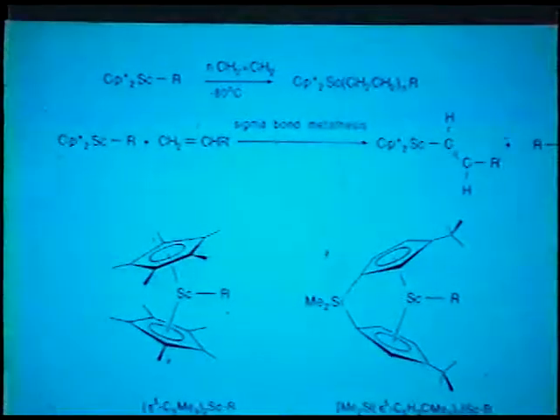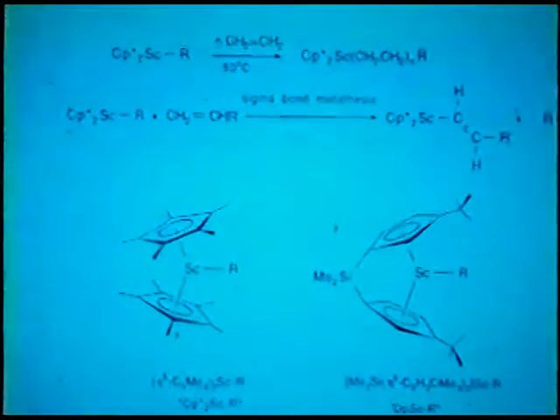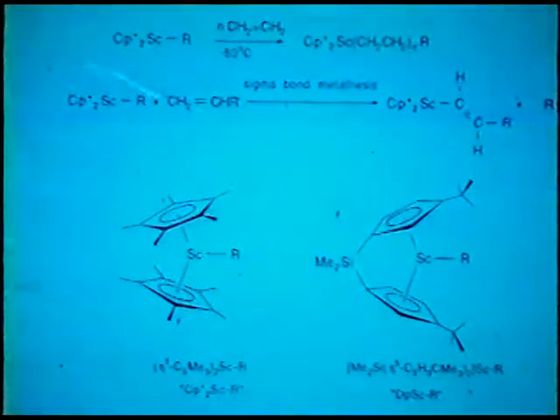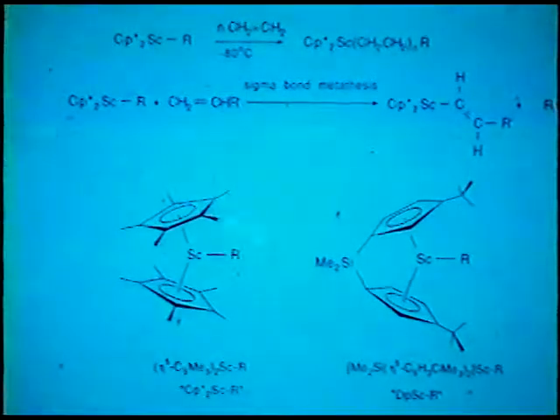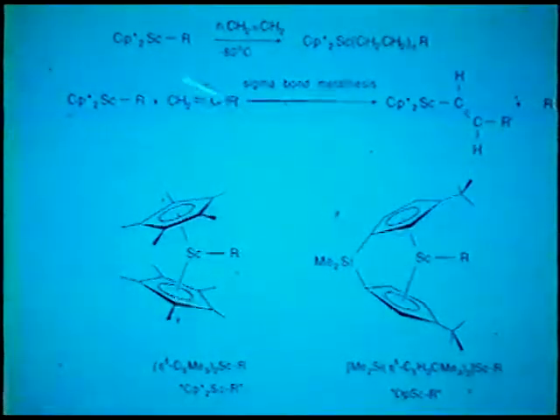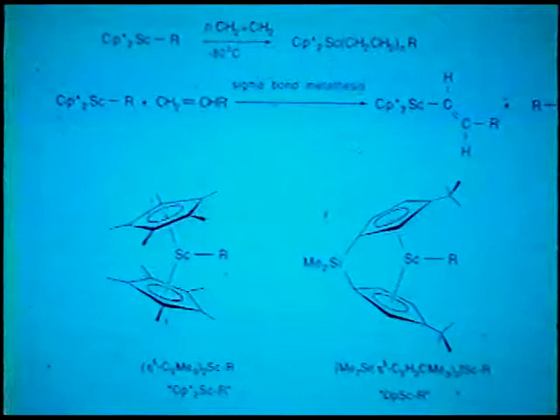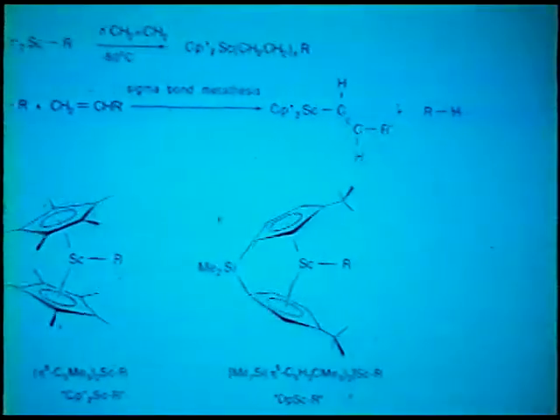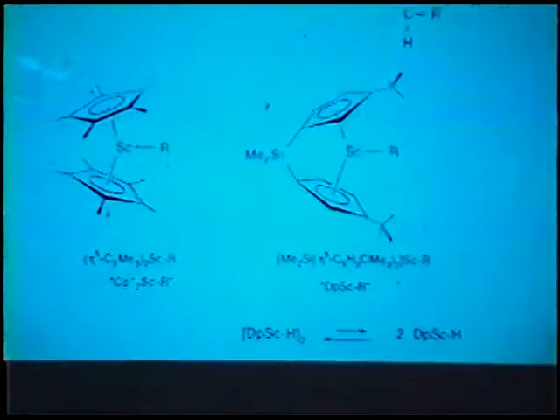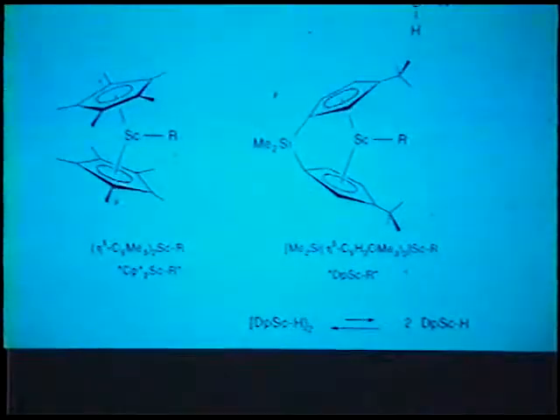Well, ethylene polymerization is nice, but of course it would be best to be able to polymerize a number of different types of olefins. Unfortunately, this sigma bond metathesis, the CH activating process I described, is the dominant process when you go to any olefin other than ethylene. That almost certainly is due to the unfavorable sterics associated with bringing the pi orbitals of the olefin up to the front two orbitals on the scandium center. One bad interaction with one of these bulky Cp* rings is assured.